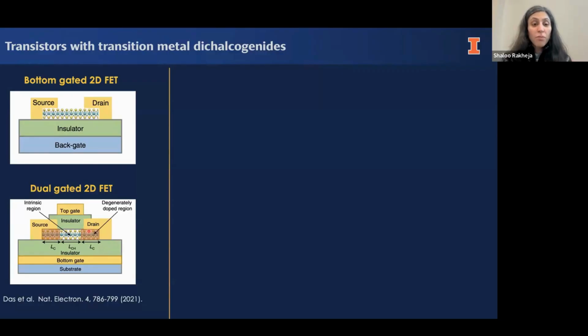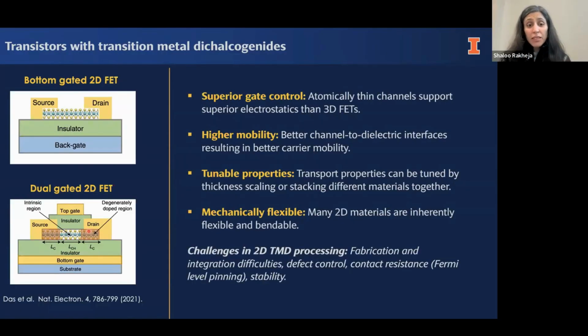People have also considered replacing these degenerately doped regions with semi-metals, for example graphene, as an example of creating those ohmic contacts. And I think one of my colleagues is working on this issue of making contacts to 2D transistors, which is very nice, because that is one of the weaknesses of this technology, where it does not compete very well with silicon. So the benefit of these is that with their atomically thin layers, we can apply a very small gate voltage to turn the device on and off, which is really great. So it can have better electrostatics.